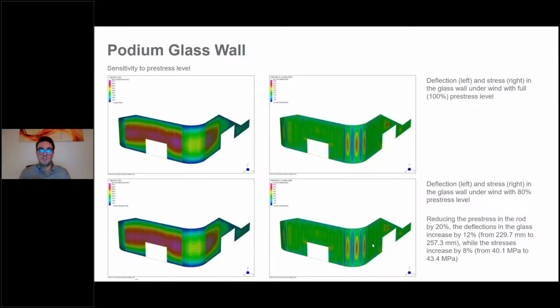One of the important things we had to do was clearly to understand the sensitivity of the glass, mainly to the pre-stress level of the rods. So we studied different scenarios for the rod pre-stress level. So not only the 100% design pre-stress, but we also analyzed other configurations with 80% of the pre-stress or up to 140%, just to have a load factor equal to the one of the permanent load as per Hong Kong standard. So obviously, it was interesting to understand what was the relationship, which is obviously not linear. So what we were seeing, especially when reducing the load in the rod, was that the deflection was increasing, and therefore also some of the stresses in the glass were higher. Therefore, we had to use this basically as a worst case scenario, mainly for the design of the glass.